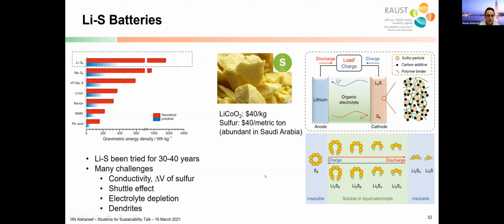Lithium sulfur battery is another type of battery that people have high hopes for. In principle, it can give you 500, 600 watt-hour per kilogram. And the advantage of this: the price of 1 metric ton of sulfur is $40. But the price of lithium cobalt oxide, which we currently use, is $40 per kilogram. So there's a huge difference in price. And Saudi Arabia has a lot of sulfur. So if one can solve the problems associated with sulfur, which include a lot of problems, really, the conductivity of sulfur is not so high.